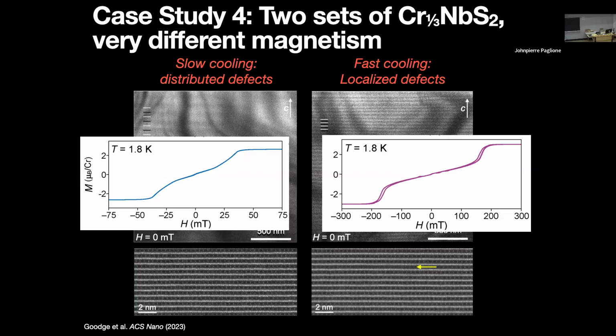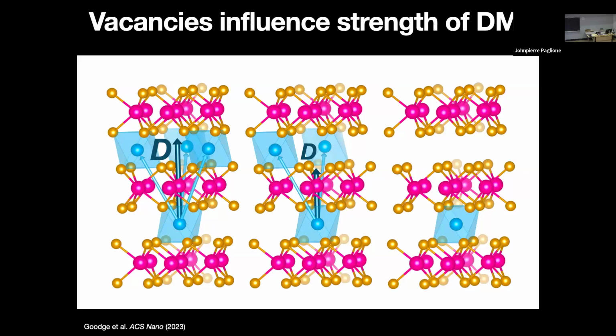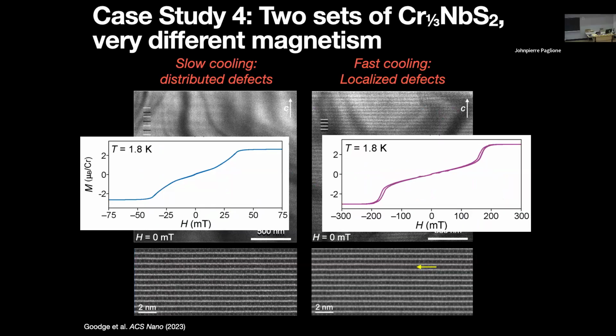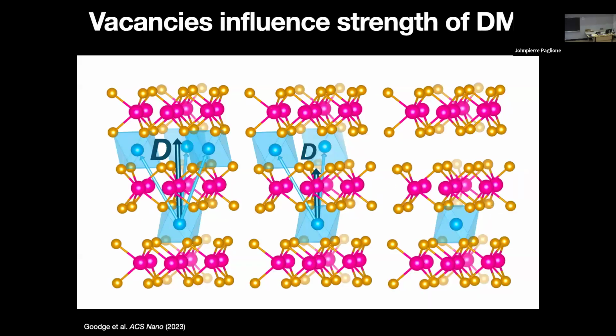And so, the way we think about this, because how else can we rationalize it? If we take as a given that the compositions are effectively identical, the way we think of it is that in this one the DM interactions are weak, because even though you have the same average number of vacancies throughout the entire crystal, when you cool slowly, you're smearing out those vacancies throughout the whole crystal. And so then you're uniformly weakening the DM interaction everywhere, leading to this sort of softer ferromagnetism. On the one on the right, when it's cooled a little bit faster, you end up, for reasons we understood later, this configurational disorder thing, clustering your defects in some regions, so that everywhere else is sort of full strength DM, and then there are regions that have no local DM.